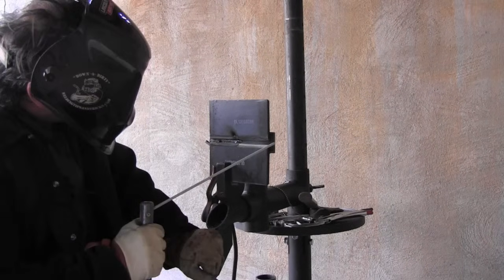I would recommend not making a tie-in but stopping there and welding toward the middle, stopping somewhere in the middle and then changing directions and welding toward that. Reason is that stopping and starting is a lot more likely to have a defect such as slag, lack of fusion, or porosity than once you've got the rod all going nice and hot and tying into a place where you stopped.